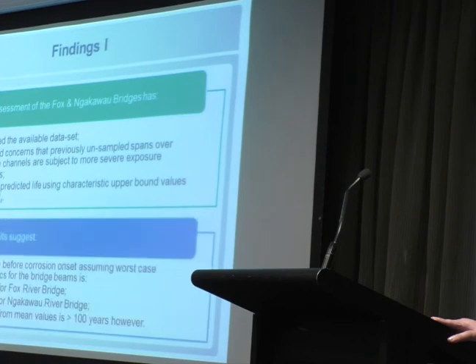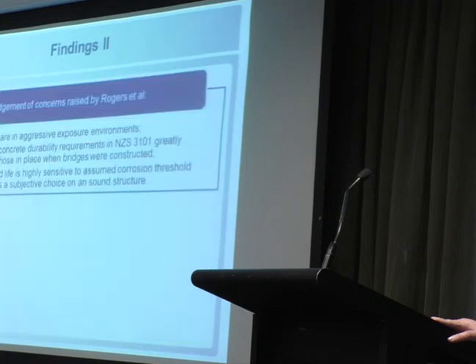The results do suggest that for the worst cases, the residual life is 47 years for the Fox River Bridge and 22 years for the Ngakawau River Bridge. But if you just look at the mean values, you do get lives of over 100 years. And I don't want to be seen to be casting aspersions on Rogers' original research. You have to acknowledge that the bridges are in aggressive exposure environments.